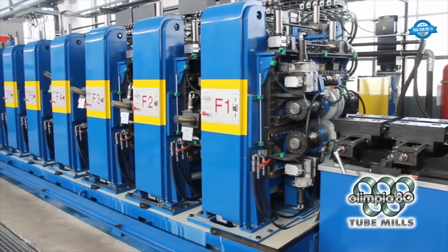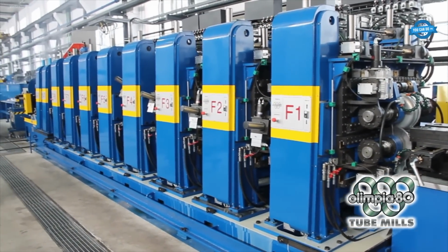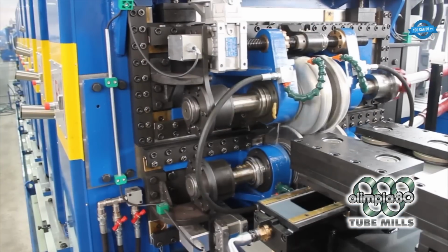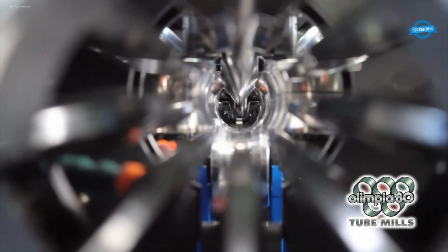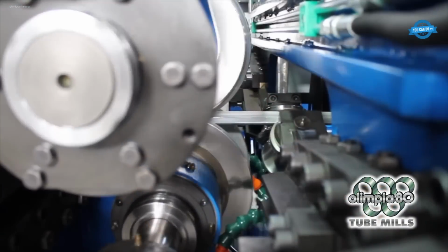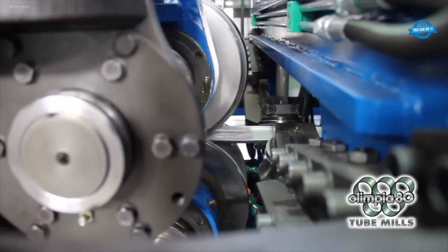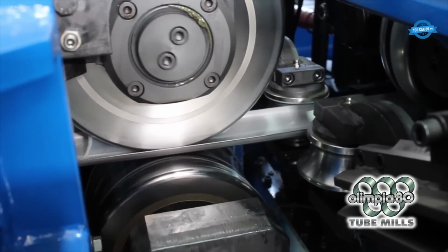This forming system gradually transforms flat strip into a round tube using a series of linear roll cages, reducing stress on the material and ensuring excellent roundness and dimensional accuracy. The HF welding unit uses high-frequency induction to join the edges, delivering a strong and precise longitudinal weld.